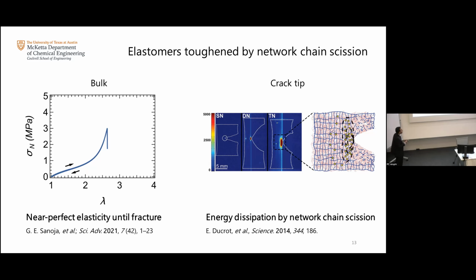So what is very neat about this model system, two things again: it's nearly perfectly elastic all the way to the fracture point, and a lot of the energy dissipation that occurs at the crack tip is because of bond breakage of the polymer network. Okay, so if I can probe bond breakage ahead of the crack tip, then I can directly probe energy dissipation in a system that is perfectly elastic. And that's actually the experimental design that we implemented.